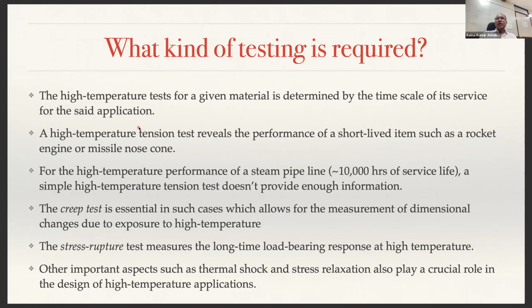For example, you can simply do a high temperature tension test. You just need to do a tensile test at very high temperature to measure the ultimate strength of the material to see whether it is going to break or not. That reveals the performance of short-lived items such as rocket engines or missile nose cones, because they are not going to be working at such high temperatures at high loads for extended periods of time. They are only going to work for a few seconds, if not minutes, right? In such scenarios, you just need to know what is the strength of this material at that particular temperature.